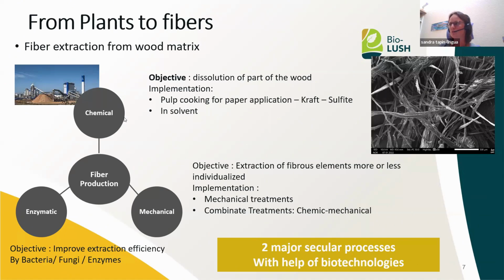If we want to produce really well individualized fibers from wood, one solution is to use chemical treatment where the non-cellulosic part is dissolved. In this case, pulp cooking for paper applications is mainly made from the kraft alkaline process or the sulfite acidic process. Treatments are made with these chemicals and high temperature, between 150 and 170 degrees approximately. This treatment allows a total lignin dissolution and to obtain individualized fibers. And in all cases, we can improve the efficiency of the different separations, chemical or mechanical, by enzymatic treatment of fibers with bacteria, fungi, or enzymes.